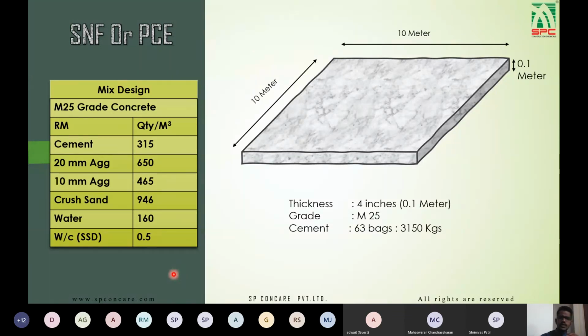For that, we have considered a case: a slab of 10 meter by 10 meter, with a thickness of 4 inch, that is 0.1 meter, of M25 grade. The mix design is as you can see in the chart. Cement is 315 kg, 20 mm aggregate is 650 kg, 10 mm aggregate is 465 kg, crushed sand is 946 kg, water used is 160 liters. Considering SSD conditions, this water cement ratio is 0.5. For this case, the cement comes to 63 bags, that is 3150 kgs.